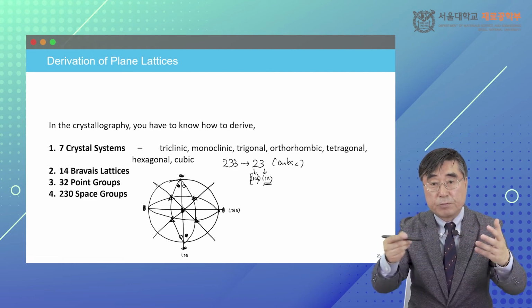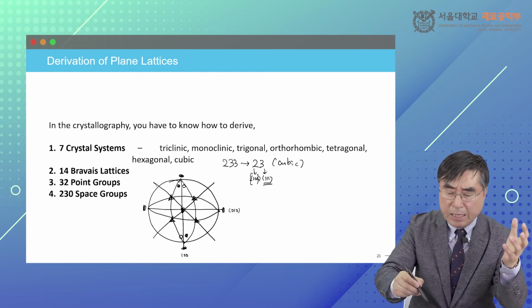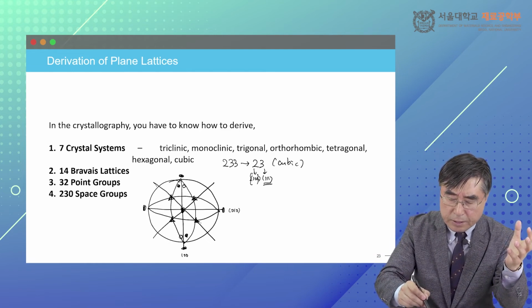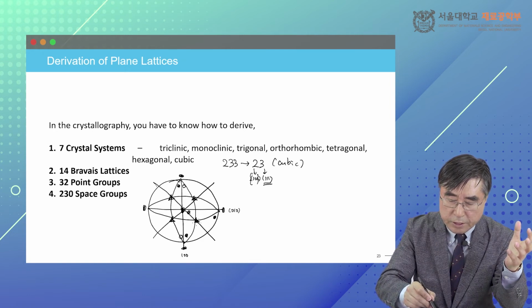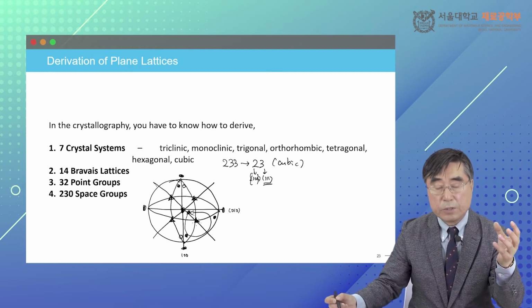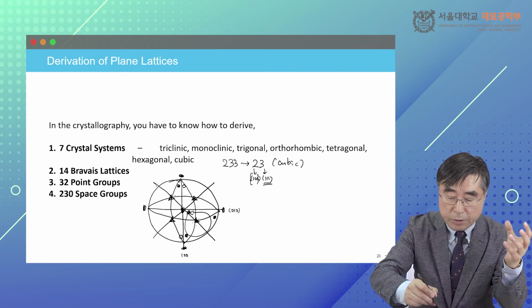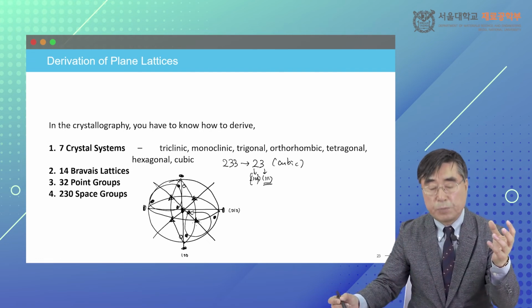That's how you find out where your poles are located. But basically, this is simple. If you think about here, this is 60 degrees, 120 degrees. The poles are generated here. This is the threefold rotation operation of this pole along this 1, 1, 1 axis. By the same token, poles are generated here. This is the threefold rotation operation of this pole.